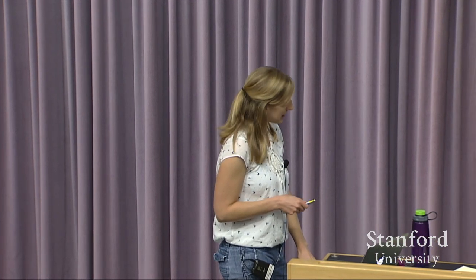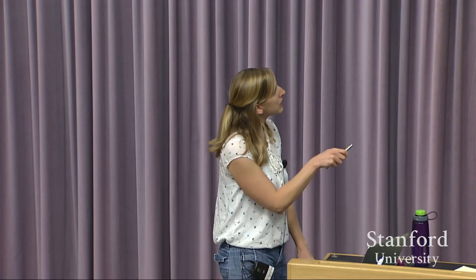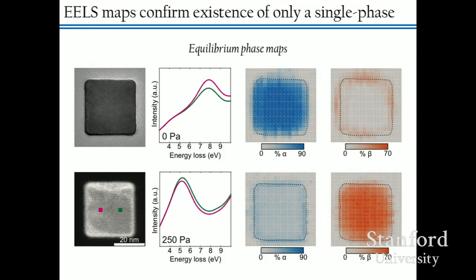Another thing we've noticed, I'll just point out, is that we can do EELS maps to confirm the existence of only a single phase in equilibrium. When I collected these spectra, I had slightly defocused the beam so that it was sampling over a large area of the particle. If we want to take EELS maps, we can focus the beam down to an even smaller probe size, on the order of 2 nanometers, and then scan it across the nanoparticle